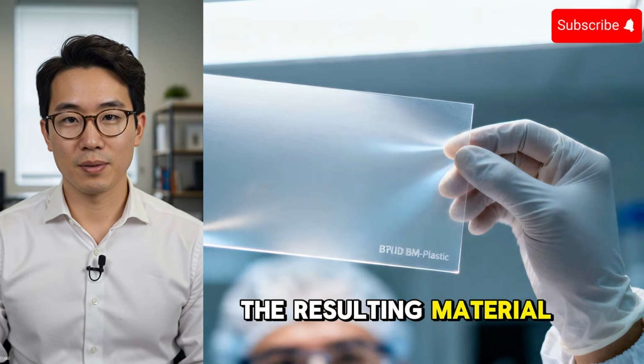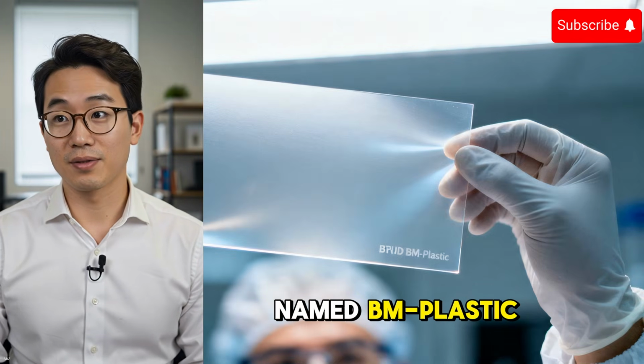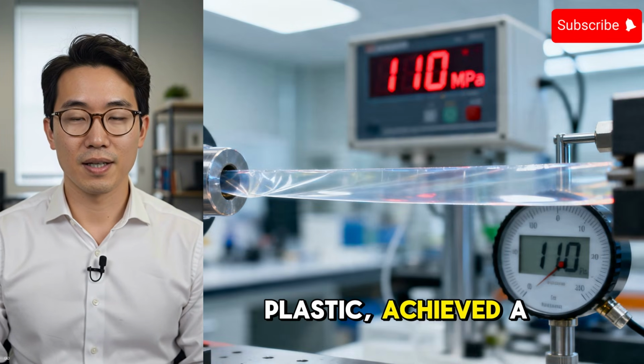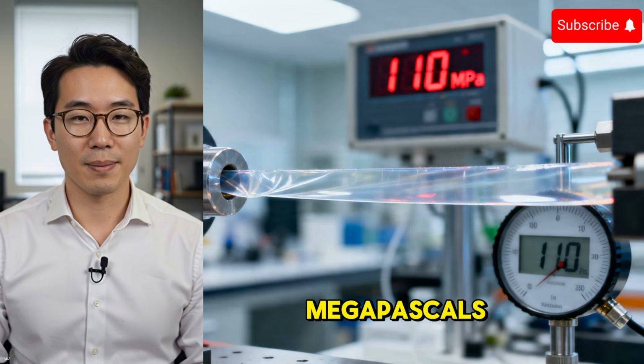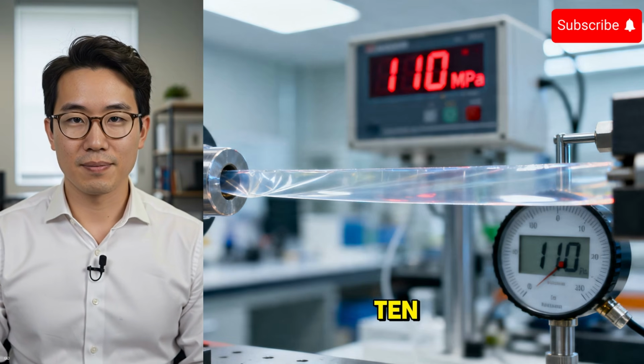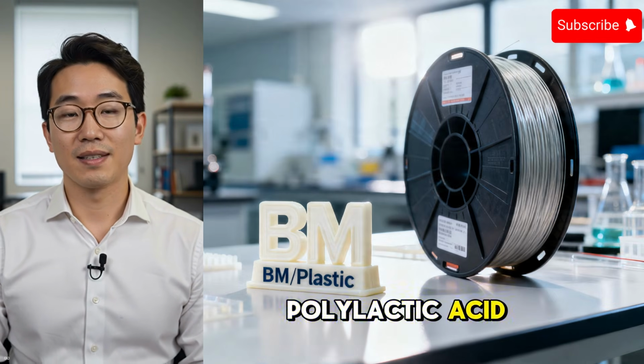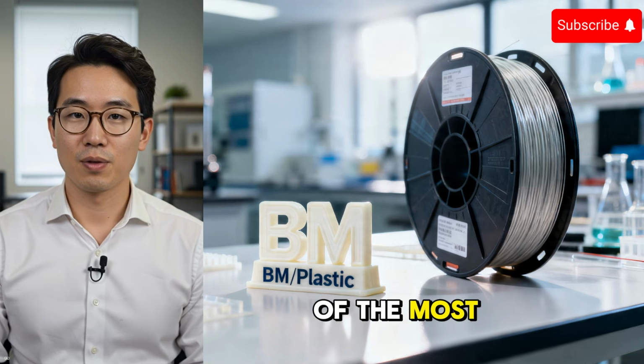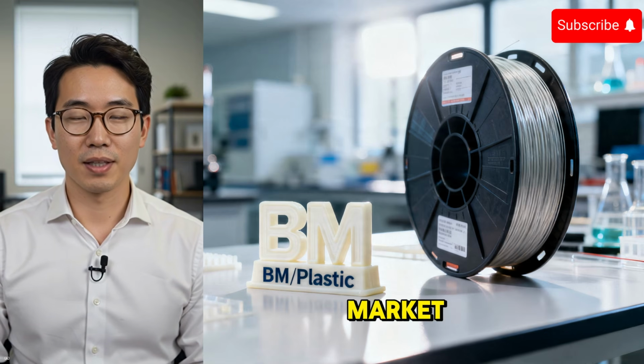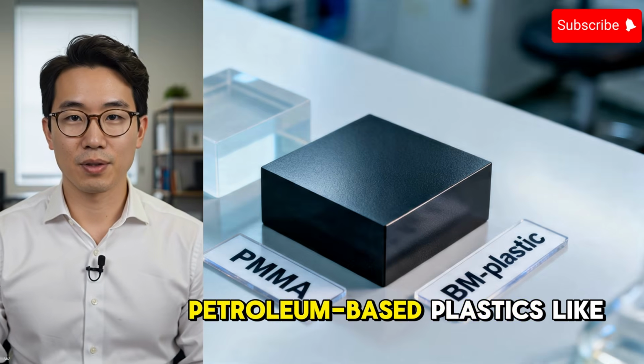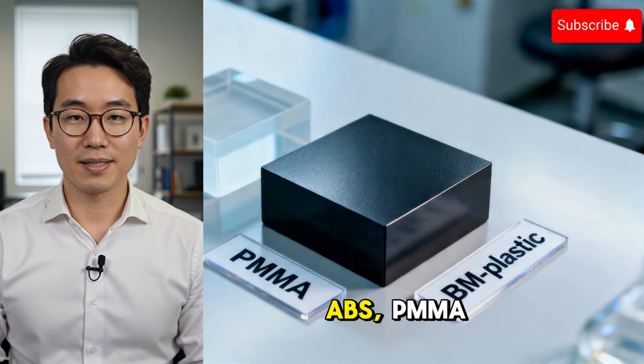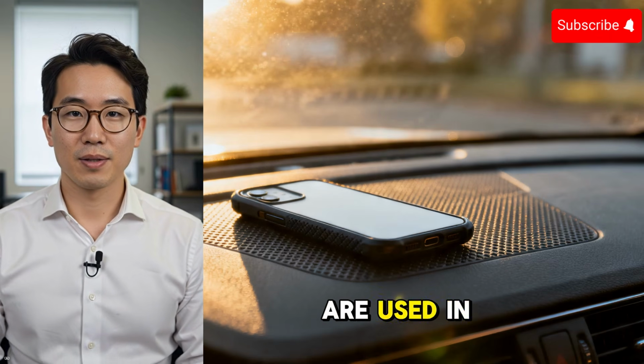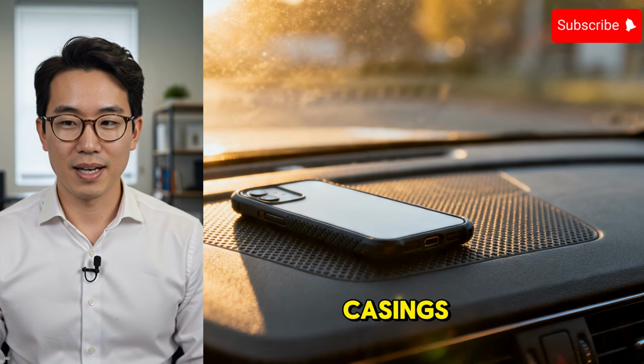The resulting material, which the team named BM plastic, short for bamboo molecular plastic, achieved a tensile strength of 110 megapascals. 110. That number alone puts it ahead of polylactic acid, or PLA, one of the most widely used commercial bioplastics on the market. And it holds its own directly against petroleum-based plastics like ABS, PMMA, and PA66, which are used in everything from car dashboards to phone casings.